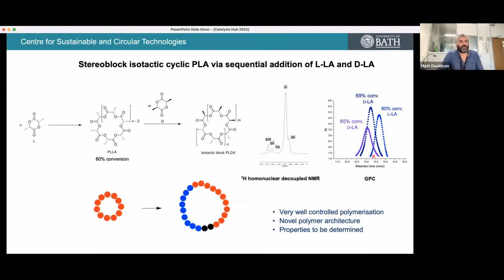Let's go to the GPC data first. This is the point at which we've got 80% conversion and we start throwing the D-lactide in there. And you can see that the polymer molecular weight keeps increasing as the D-lactide is converted, and the last sample was 85% conversion there. So that's highly indicative of having one ring with two stereo blocks involved in it.